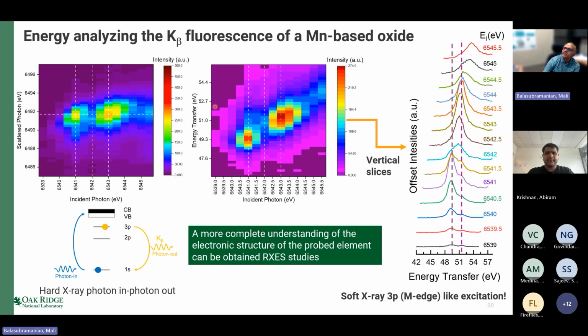Now you will see that this energy transfer has energies which are very similar to an excitation from the M edge or a 3p excitation. So this is like saying that you're taking an electron from a 3p level and exciting it to a conduction band. So this is now soft X-ray like information. So this energy transfer plays the same role as the incident energy in soft X-ray. And so you're getting soft X-ray like excitations using a photon in, photon out method. So this is a very powerful way of getting a complete understanding of the structure, but you do need a detailed understanding of it.